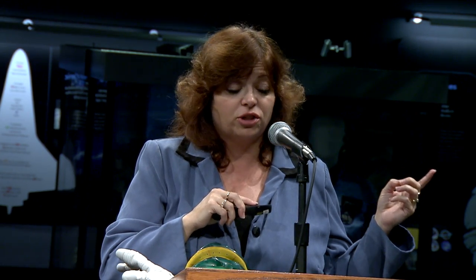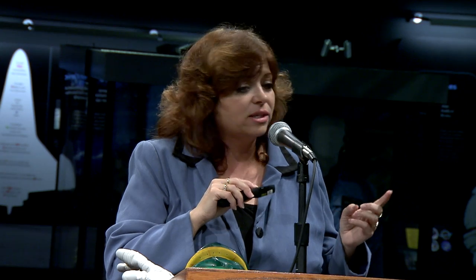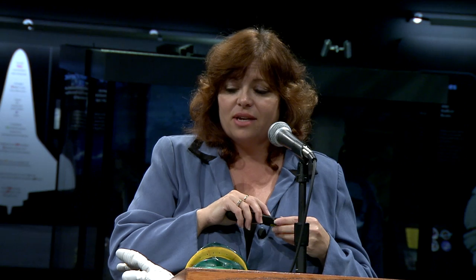And one of the suspects was handrails that have been hit by that micrometeoroid debris, and it creates these craters with very sharp edges. So we had to protect against cut and puncture. So turtle skin provides us that, because you can't puncture it, and it's very cut-resistant material when it's made out of the Vectran. And then we also use high strength, high tenacity polyesters and nylon fabrics throughout the suit as well.